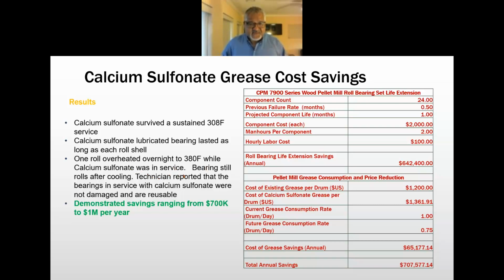But it stayed in service, and once that roll was torn down or pulled out of service, it was still rolling after cooling. The technician reported that the bearings in service with calcium sulfonate were not damaged and are reusable, even though it reached 380 degrees Fahrenheit overnight.